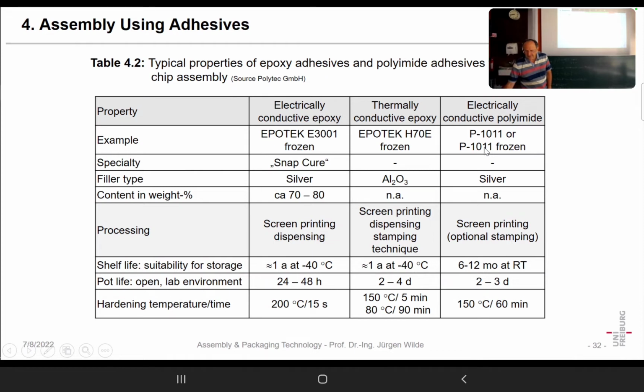Another material that can also be used, which has the advantage that you can operate the devices later on up to 250 degrees centigrade, is silver-filled polyimide. Polyimide is much more stable at higher temperatures than epoxy. Normally, you would say the limit for epoxy is 200. On the other hand, the short time limit for polyimide is maybe 300 to 350 degrees centigrade. That means you can operate polyimide adhesive joints at 100 degrees higher than epoxy joints.